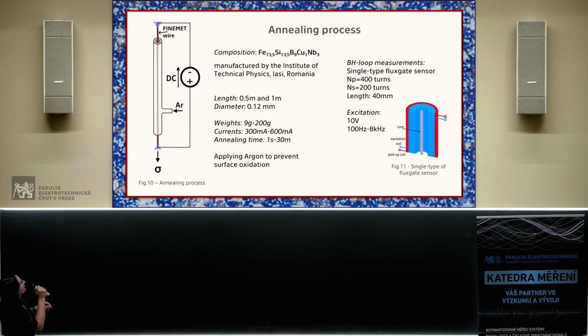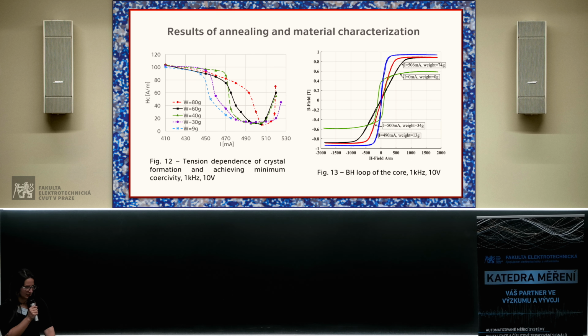This is our annealing setup. It's a tube filled with argon gas to prevent oxidation, because we found out that when annealing is done in oxygen, the wire could be oxidized, and coercivity could be much higher than in the as-cast alloy. So we apply current to heat it up. And then we test it in a single-type fluxgate sensor just to build a BH loop and characterize our material. Here are some results of the characterization.